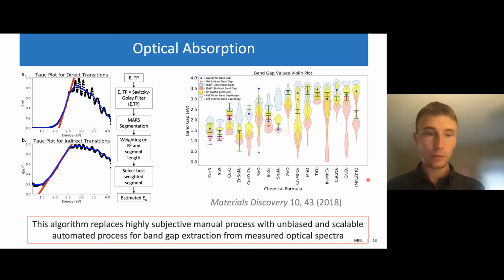I'm not going to say too much about this except to highlight that this algorithm replaces often very subjective manual process that is quite often biased in extracting bandgaps out of experimental measured optical absorption spectra with something that is much more unbiased, mathematically consistent and scalable to be applied across tens of thousands of optical absorption spectra that are measured and reported in HTEM-DB for extracting bandgaps out of the spectra as a quantity that can be directly compared with theoretically predicted bandgaps.